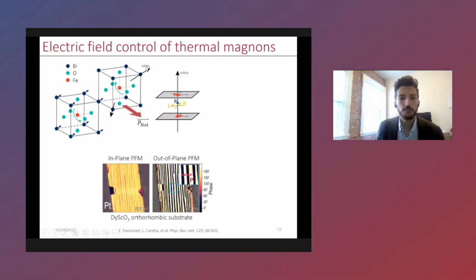If you look carefully, the out-of-plane polarization cancels out, but there is a net in-plane polarization. I'll spare you the details, but we can measure this net in-plane polarization using techniques like piezo force response microscopy, which is shown here. And this is exactly what the structure looks like that we've designed in between 2 of these non-local electrode devices, using platinum as our electrode contact.